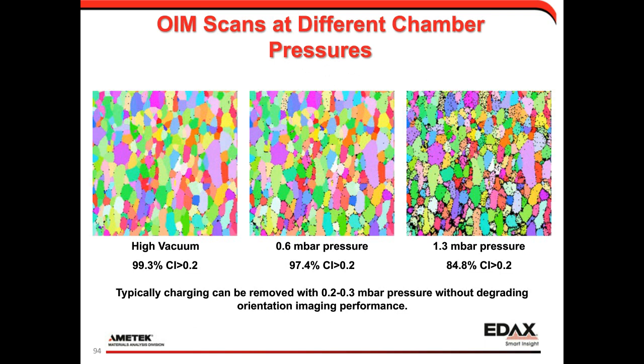And you can see in this slide, this is an example where at high vacuum we're at about 99% indexing there on the left. We put in that 0.6 millibar pressure, drops down to about 97%. We go into more 1.3, it drops to 85%. And you can see that generally the indexing starts to fail towards the grain boundaries. And that's just where your pattern quality is a little bit worse to begin with. You can have overlapping patterns anyway. Luckily, typical charging can be removed with just a little bit of pressure. And so you can put in 0.2, 0.3 millibars of pressure without really degrading the mapping performance of a system.